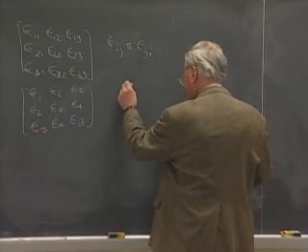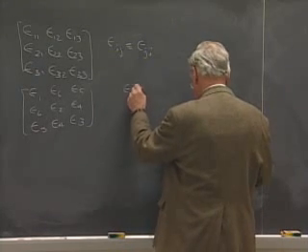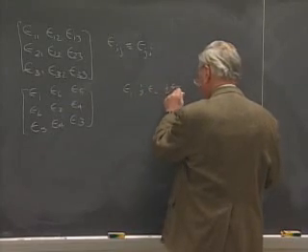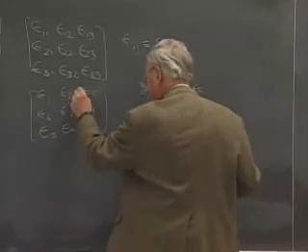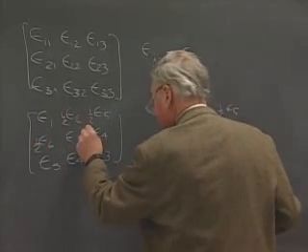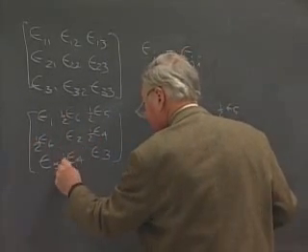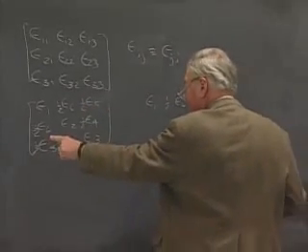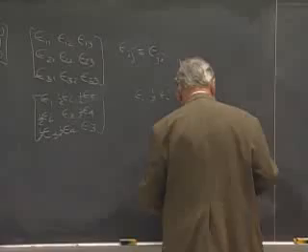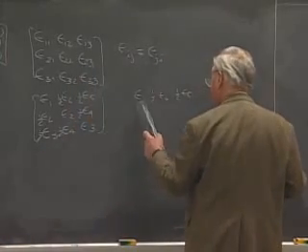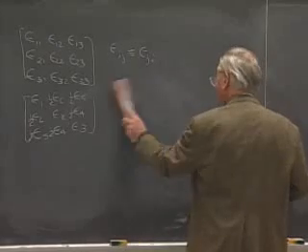So there is a factor of 2 built into the off-diagonal terms, and what we have put in here is we converted this to actually epsilon 1, 1/2 epsilon 6, 1/2 epsilon 5, and I should have written it this way to begin with. So all of these factors of 2 appear, so that when we combine these epsilons, we get a nice, clean matrix relation between stress and strain that doesn't involve factors of 2.